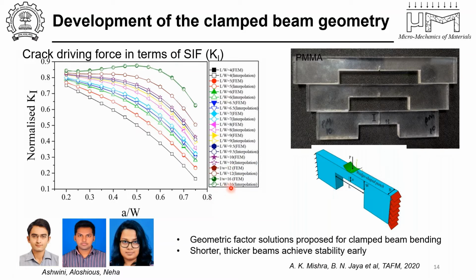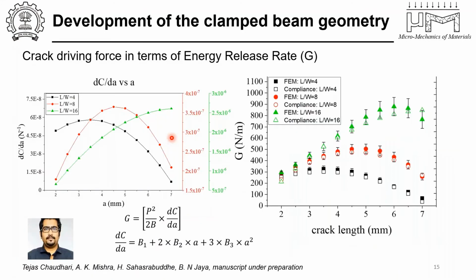If you want to achieve stable crack growth, then what we would need is a smaller aspect ratio specimen. So what we recommended is shorter, thicker beams achieve stability early and therefore can be used. But we've provided the geometric factor solutions for various L/W ratios. So if you make a beam of different values, you can still obtain the fracture toughness using these solutions that we provided. So basically, we did these measurements, which I'll come to later.